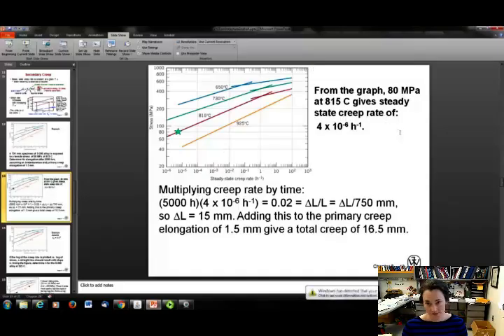That's my epsilon dot. And then what I can do is it asks me for 5,000 hours, so I can multiply my creep rate by my time. So I have 5,000 times 4 times 10 to the minus 6, and I get 0.02, okay? So that's my creep rate. So that'll give me my creep. If I multiply my creep rate by my time, I get my creep. And that's equal to, remember, the strain, which is the change in length over the length, which is the change in length over the initial length of 750 millimeters, okay? So that means I can solve for my elongation, and it's 15 millimeters. And that's for my secondary stage. If I add that to the primary creep, I get 16.5 millimeters of elongation of that part. Hopefully that helps.